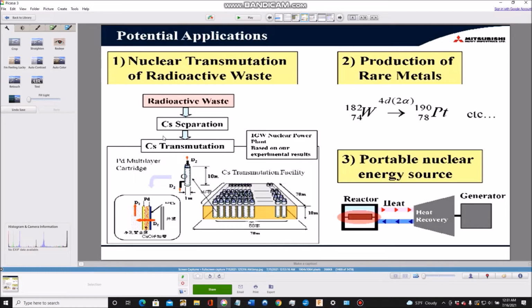So in the case of transmutating tungsten into platinum, you're going to use 8 neutrons. So you go from tungsten 182 to platinum 190, and you're going to add 4 protons. Deuterium gas costs something. Well, deuterium gas uses about 200 to 1,000 kilowatt hours per kilogram of heavy water. And so when you electrolyze the heavy water, about 24% would be deuterium. Water is about 11.8% hydrogen, so deuterium has twice the mass. So you're looking at a pretty significant energy expenditure for producing the deuterium.